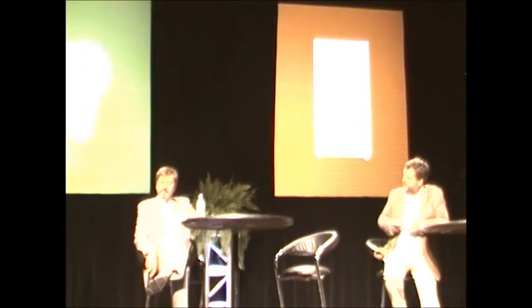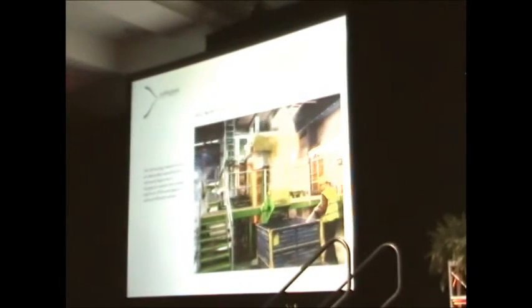It was pretty good. You can see that this is looking at it from the front end, and you can see the molten glass coming out of it. We have 2 options for taking the glass out, from both sides. In the film that I'm about to show you, it's coming out from the other side. It starts off with a pipe coming out of some crushed glass. It goes into a hopper, which is where the glass is mixed with the chemicals, and then goes into what you'll see is a long orange tube that starts to feed the glass into the furnace.